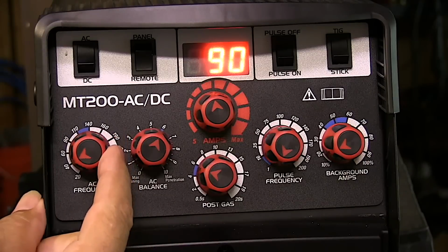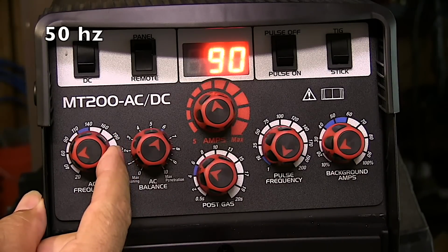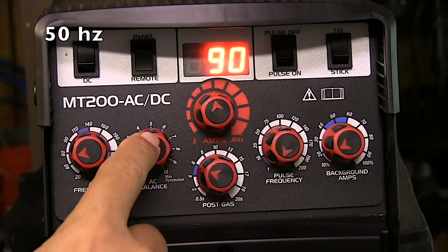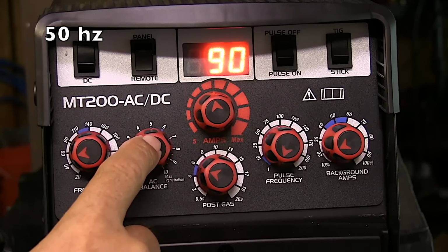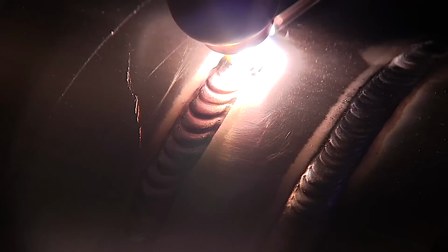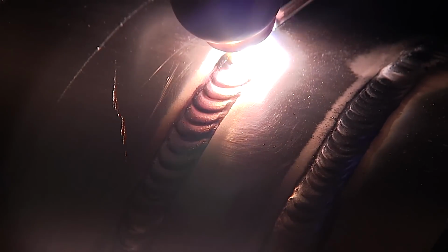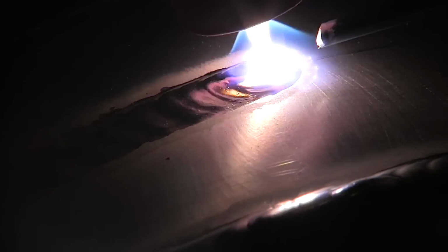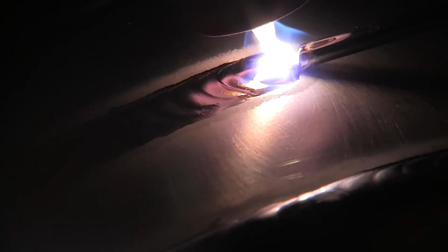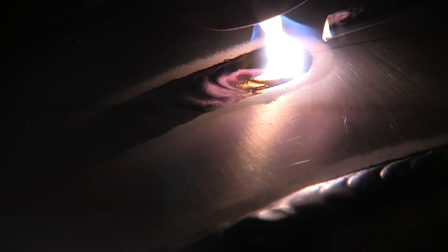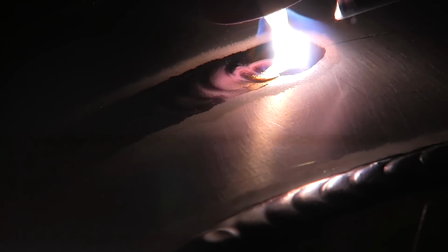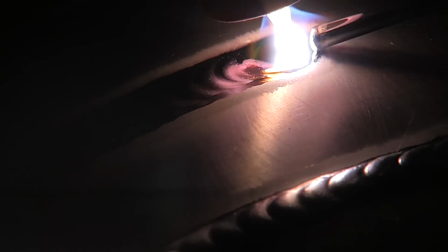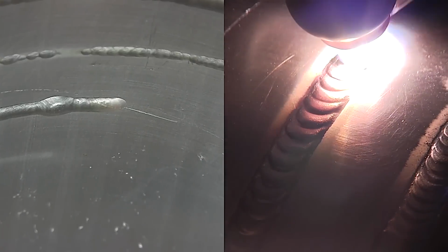If you leave the amperage the same, there's a definite difference in the amount of penetration that you'll get at a low frequency versus a high frequency. In my experience, the low frequency is going to get more penetration at a set amperage. Here I'm at 50 Hertz. I'm on a fixed rotator. This wall thickness is about 90 thousandths thick, if I remember right. And at 50 Hertz, this is penetrating all the way through, no problem.